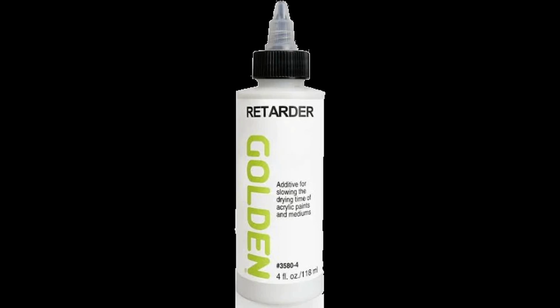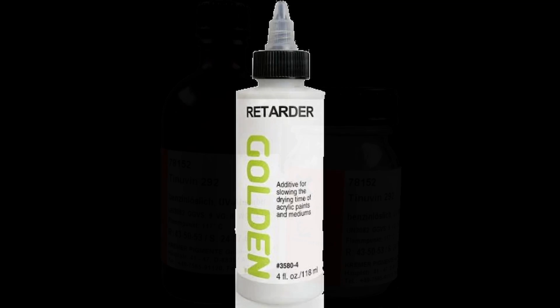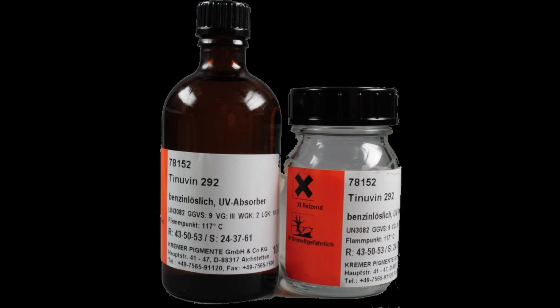Another way to sometimes help that, especially in solvent-based acrylics where drying times are very fast, you can have a retarder. These tend to be solvents with similar miscibility properties, but a lower volatility, leading to longer drying times that allows the paint to settle better before the solvent evaporates. The last additive, which can be equally applicable to both solvent systems, are UV inhibitors. These are compounds that absorb or otherwise deflect the damaging effects of UV radiation on a paint to improve its long-term appearance.